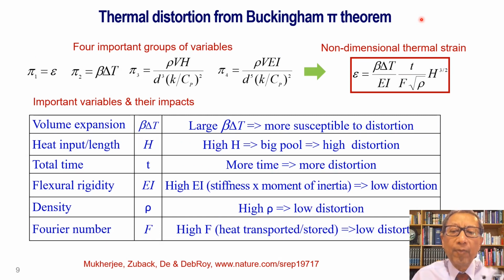To build a model for thermal distortion, we use scaling analysis based on Buckingham Pi theorem. The important variables are listed here. Volume expansion is the product of volumetric thermal expansion coefficient multiplied by temperature change, heat input per unit length. If the heat input is large or if the volume expansion is large, the part will be more susceptible to distortion. Similarly, if the total time taken is large, the part will be more susceptible to distortion.